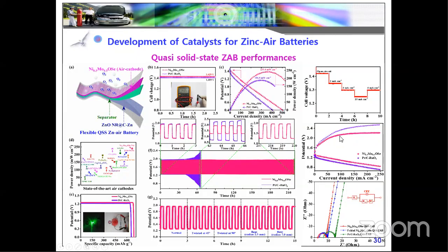And finally, you can see the different charge-discharge curves with different comparative materials. For our catalyst, you can see the anodic and cathodic potential difference is very close compared to the commercially available catalyst. From the studies, we can see our catalyst is more active towards metal-air batteries.